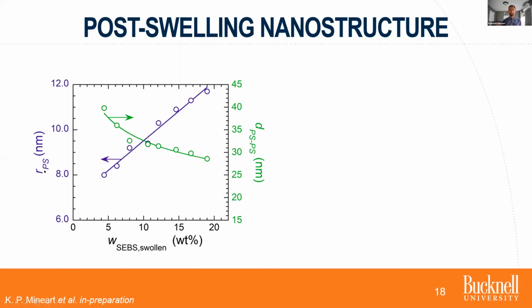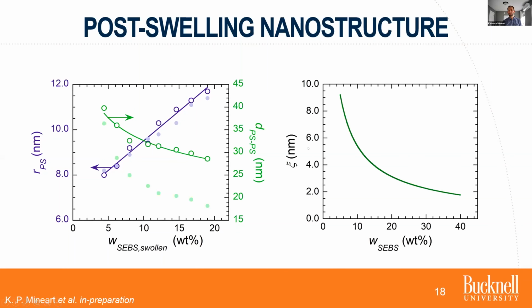Not much of that mineral oil, if any, is going into the polystyrene domains because it's chemically incompatible. The x-axis values won't match up here, but just for comparison to what we started at, these lighter points are the gel structural parameters before pre-swelling, and the open symbols are post-swelling. And so like I mentioned, the radius of the polystyrene domain is staying mostly constant, whereas we see a serious dampening in the drop of spacing between polystyrene domains based on the swelling behavior. So just something important to keep in mind. The other thing here is that the mesh size calculation doesn't change based on triblock copolymer concentration. The biggest thing to adjust for is the fact that instead of 40 weight percent as our highest concentration, now our gels start around 19%.